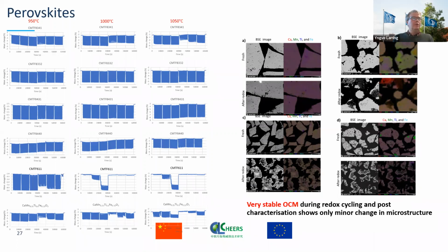So the 8431 showed really good performance and was taken further in China for upscaling, which will be presented by Lilu afterwards. 611 is the same one that has been running successfully with this CLOU material, showing very good performance for methane combustion below 950. But we see that this material does not work at 1000 and 1050, meaning it's very important to design a material that fits the purpose and the window of operation for the CLC conditions.